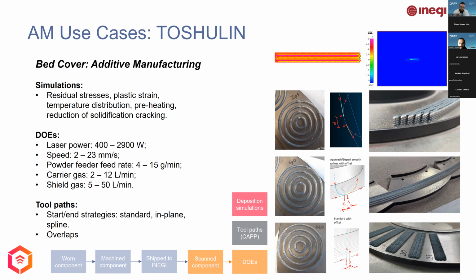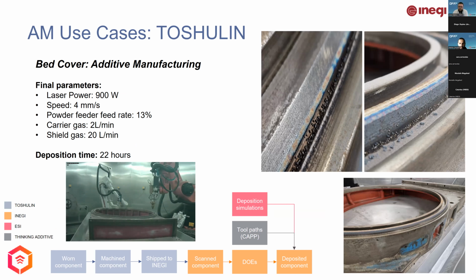After arriving at a good set of parameters and strategies for the deposition on the bed cover, the additive process seen in the video below was performed. After each layer was done, a visual assessment of the result was performed. Between layers, a 20-minute wait time was established in order to allow the part to cool down to room temperature, avoiding the development of cracks in the material. The deposition process overall took 22 hours to complete.